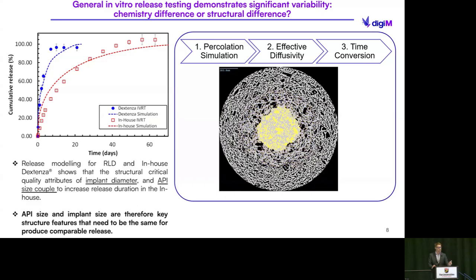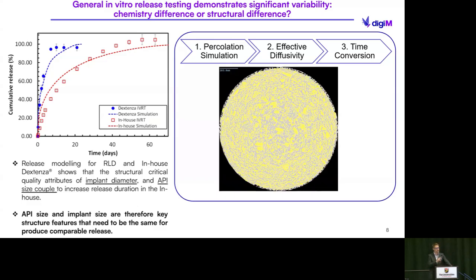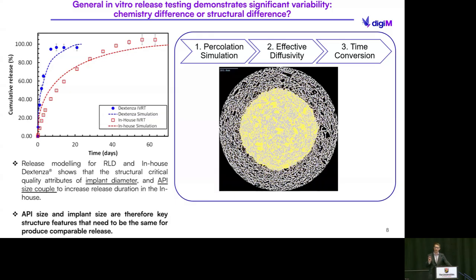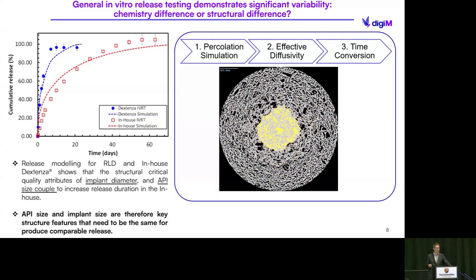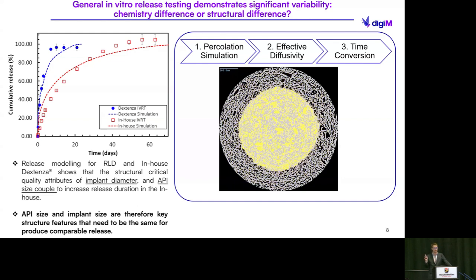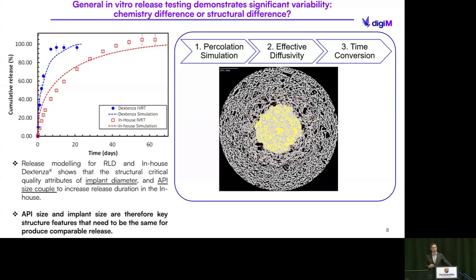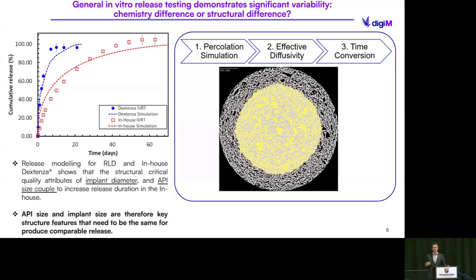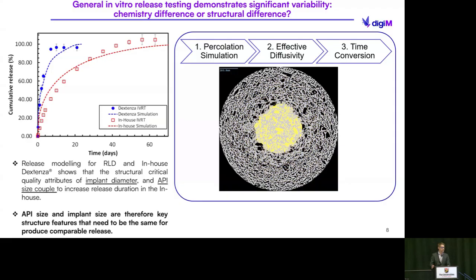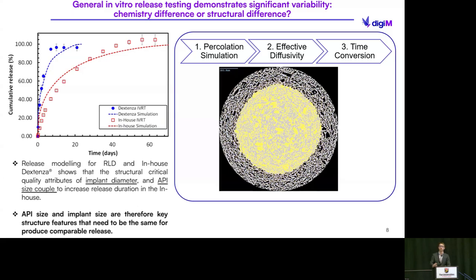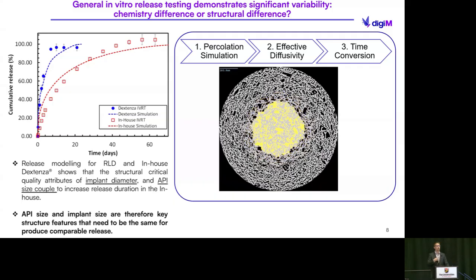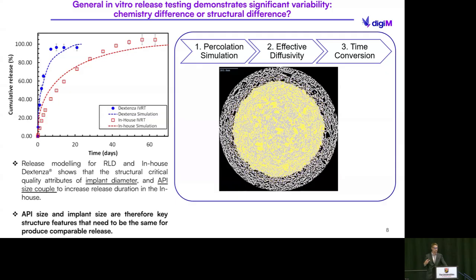The other fascinating thing that we didn't move forward with here yet, simply because we didn't have an in vitro release method with which to compare against, is that we can choose what direction we're allowing to be the source of diffusion. So in this case, we're allowing the radial direction to be the primary diffusion pathway, following the physics of it. But we can also choose to allow only diffusion going along the main axis, which may be more instructive and more related to a biorelevant simulation.